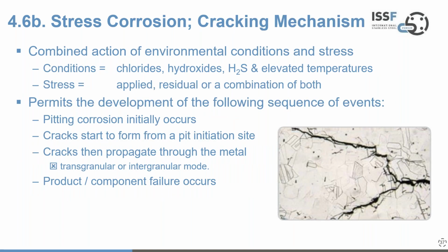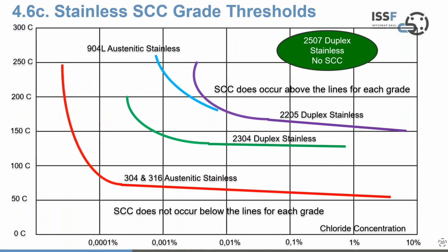So if we look at the mechanism. Here, we know that pitting corrosion initially starts with stress corrosion leading to cracking. And often you've got associated with this chlorides, not exclusively. So higher molybdenum grades will certainly give you some significant benefits here. But if we go to the threshold diagram, which I just put back on screen, what you will see here is 316 is an austenitic grade, as shown by the red line on this chart. Whilst it has some resistance to stress corrosion cracking, it's fairly limited because even in an environment with 0.01% chlorides, you couldn't operate above about 65 degrees centigrade.